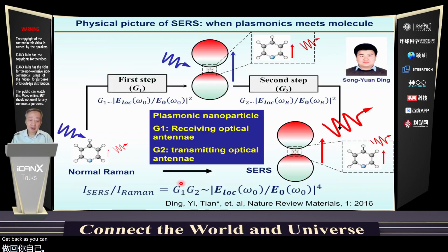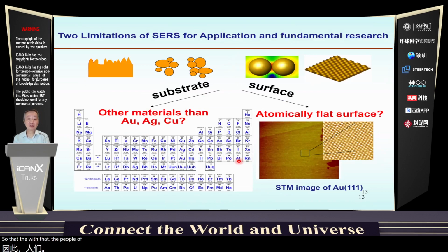As you can see, the enhancement factor is the SERS signal intensity in comparison with the normal Raman intensity. But we should realize that because it's the fourth order, if the field changes about 100 times, then the enhancement factor will go to 10 to the 8th. That is huge, right? So with that, people were very happy.